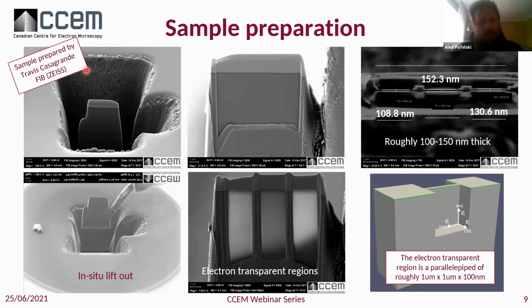To do that, we need to first isolate a very small section from your 3D structure. So here there's going to be the lift-out. You take a small piece and you connect it to a support, like here a grid. And then we will do the finer thinning by creating those window regions. You can create one or multiple. Here the idea was to create multiple ones to have different thicknesses. And so the idea here is that you generally have this type of structure at the end. You have a region relatively thick, micron scale thick. And you have in between a window region, so I'm going to call these pillars, and you have in the middle a window region that is thin, roughly 100 nanometers thick.